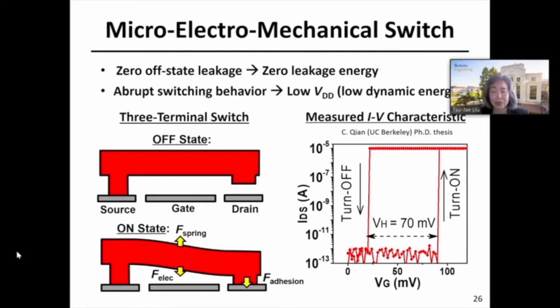logic. So my group has gotten switches to work down to below 10 millivolts switching voltage, and we've demonstrated circuits down to about 25 millivolts VDD. So you can get very low dynamic energy consumption as well as zero leakage energy consumption with mechanical switches. Okay, and there are other benefits of mechanical computing. They're radiation tolerant. They operate over a very wide range of temperatures. For transistors, the electron energy distribution is highly dependent on temperature, so your leakage current is exponentially dependent on temperature, and they are subject to irradiation as well.